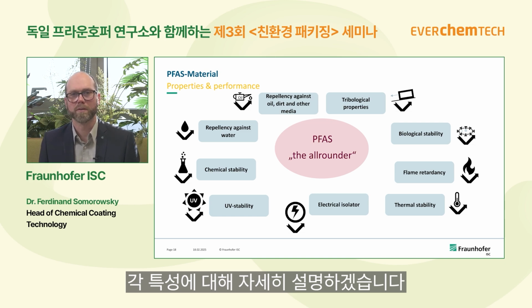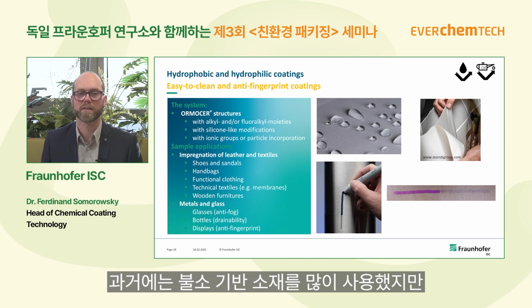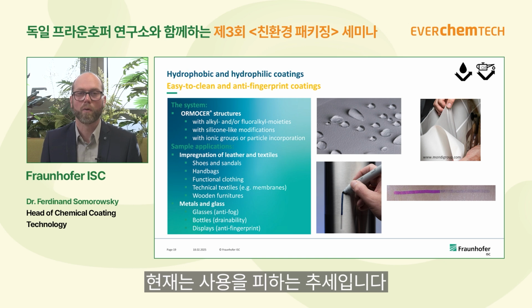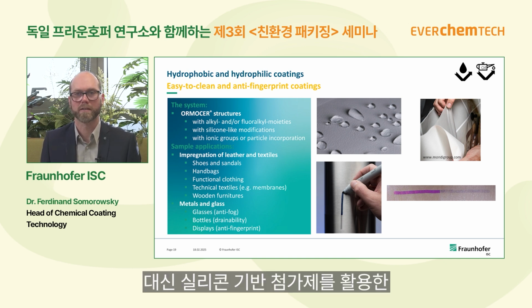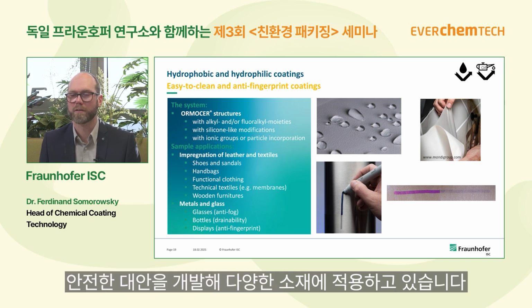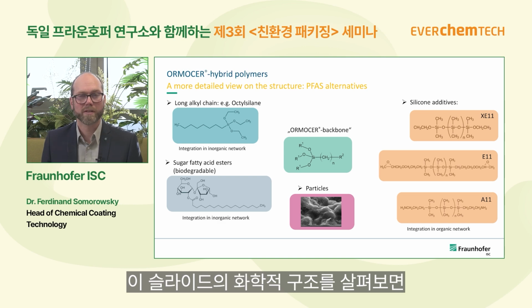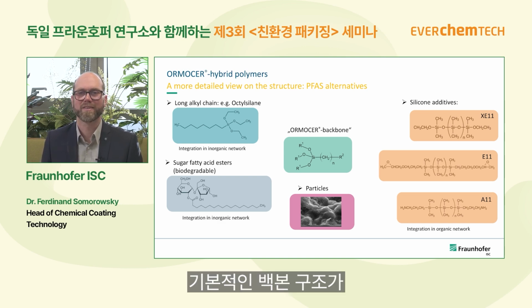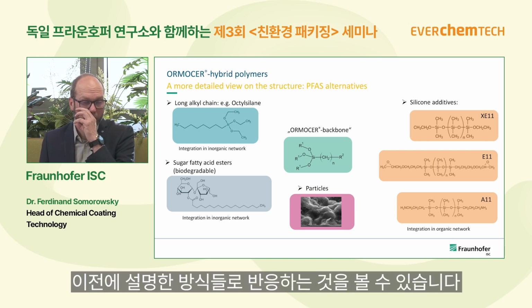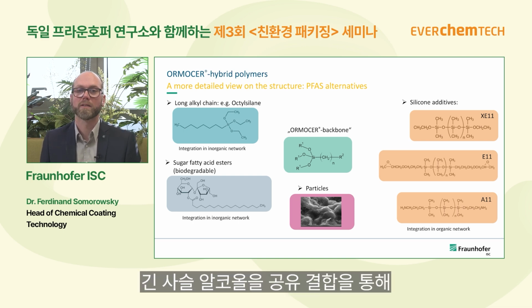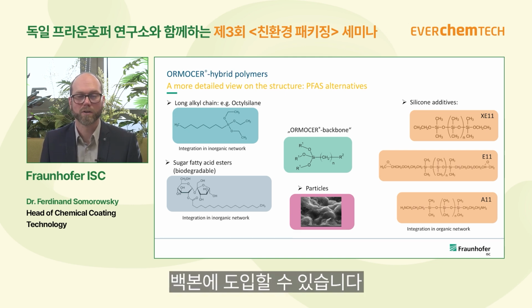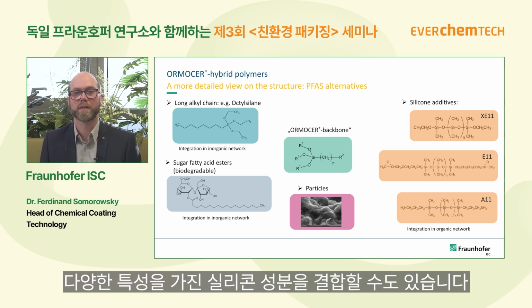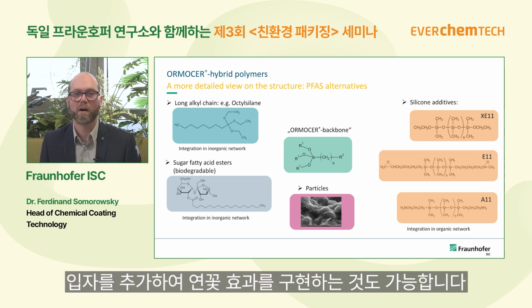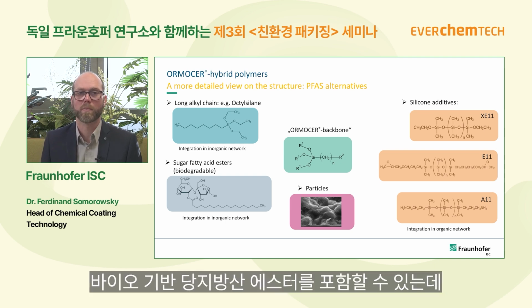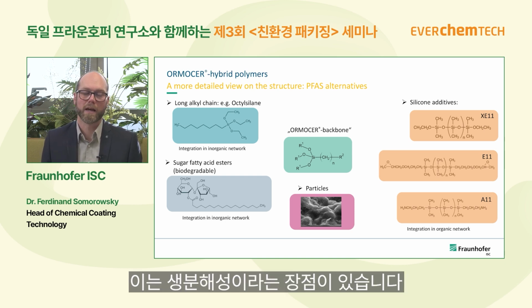We used fluorosilane materials in the past, but now we really avoid this, and we found alternatives, especially in some silicone additives, and here we can equip different materials with such coatings. When we look at the ORMOCER in detail, with a little bit of chemistry on this slide, we have our ORMOCER backbone, which reacts as described before, and we can, for example, introduce long alkyl chains, for example octyl silanes, which are connected by covalent bond to the backbone. We can also integrate different silicones of different properties, integrate particles for the lotus effect, and also use bio-based sugar fatty acid esters, which can also be biodegradable.